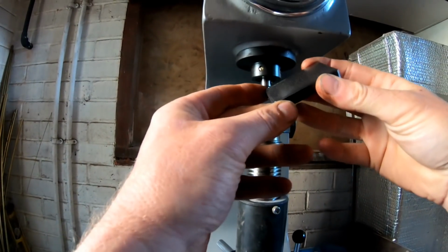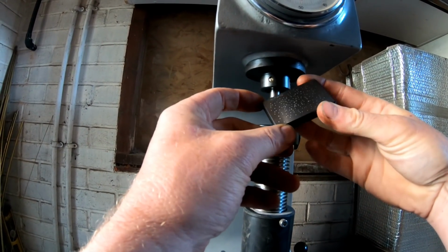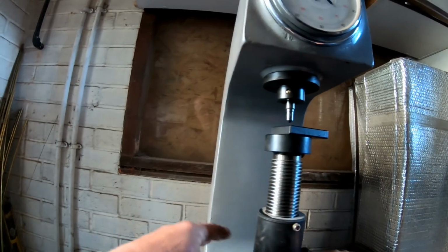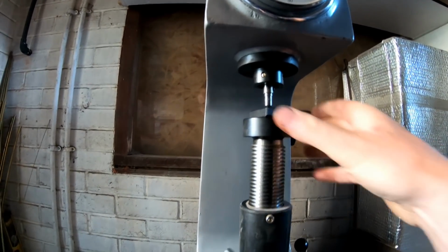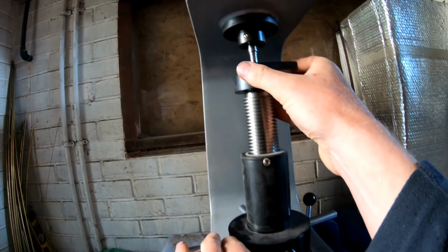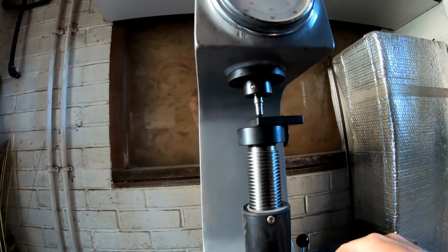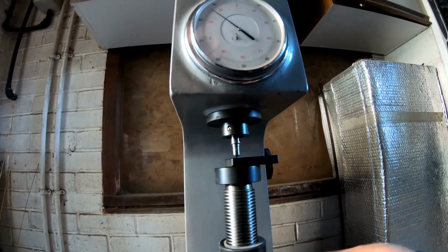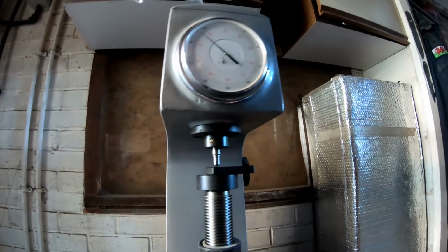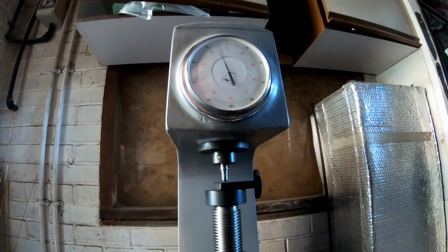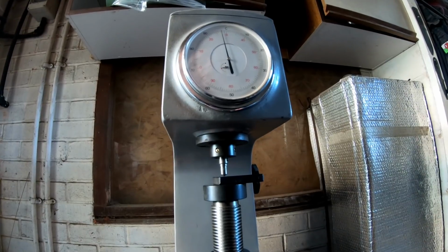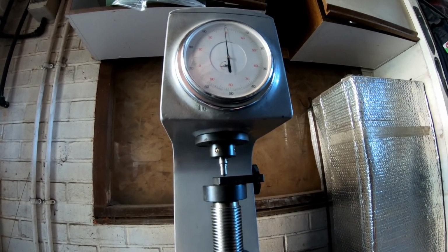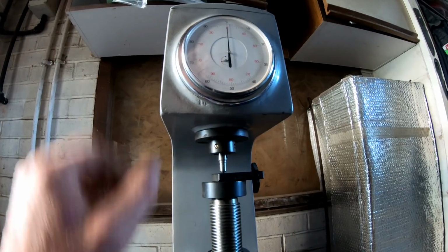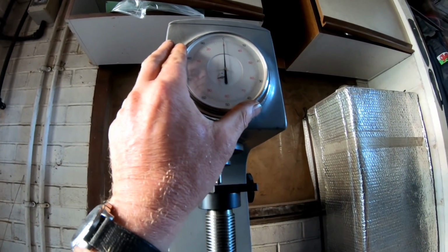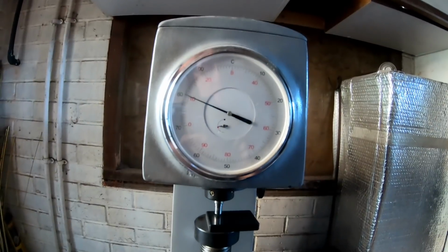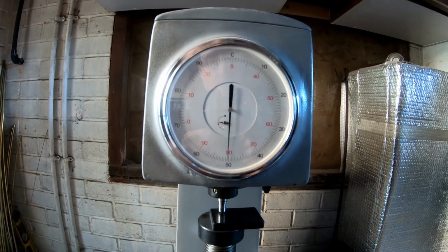Now, I know this is a measured 60.9 HRC. So I'll take a measurement from this, and if this is low, I know my blades are low. If this is high, I know my blades are high. And if it's reading around about 60.9, I know I'm more or less there. So we'll see how accurate the Rockwell tester is.